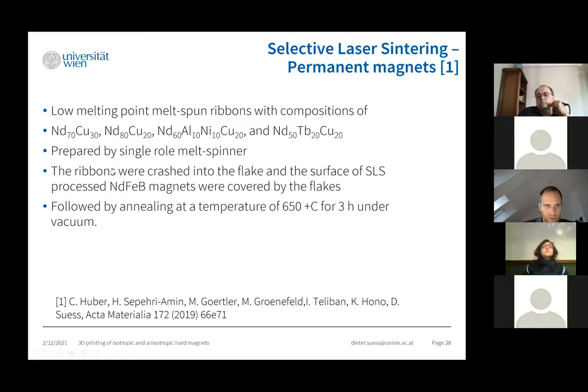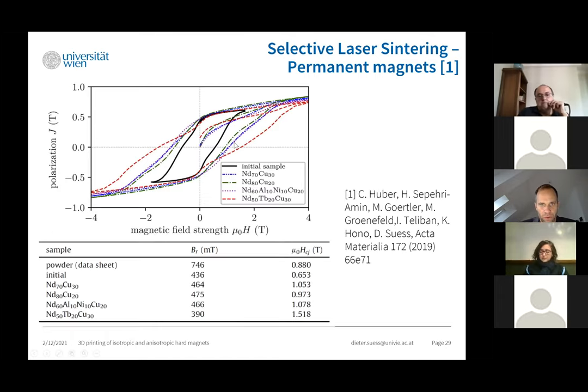So these flakes were crushed and put on the surface of the selective laser sintered magnet, and then annealed at 650 degrees Celsius for 3 hours. And due to this infiltration process, one can see that the hysteresis of the initial sample could be significantly enhanced, somewhat at the cost of the remanence. But as we hoped, one can really increase the coercivity by this infiltration process.